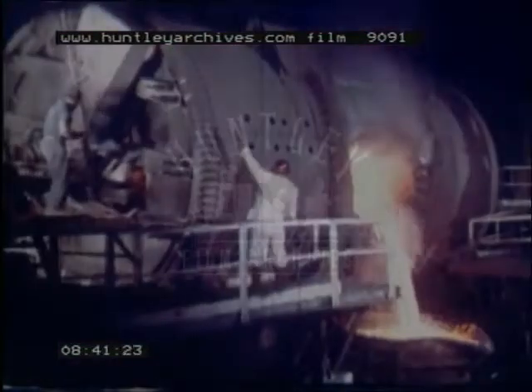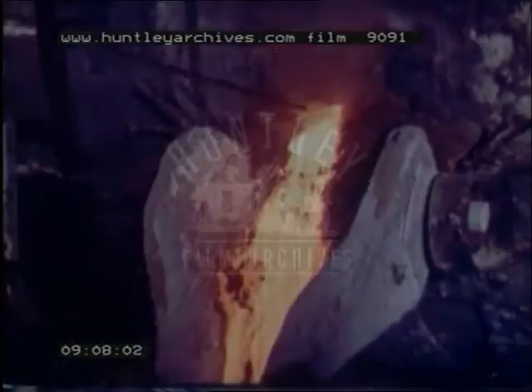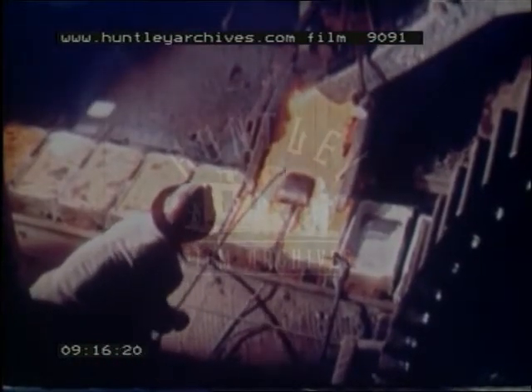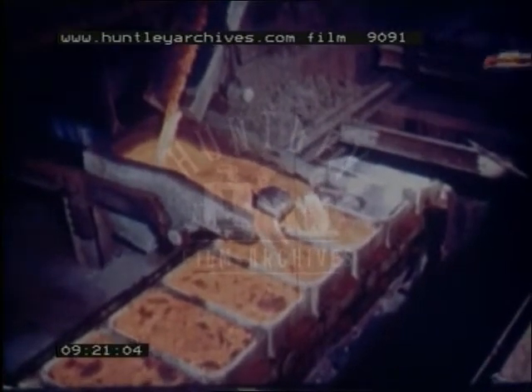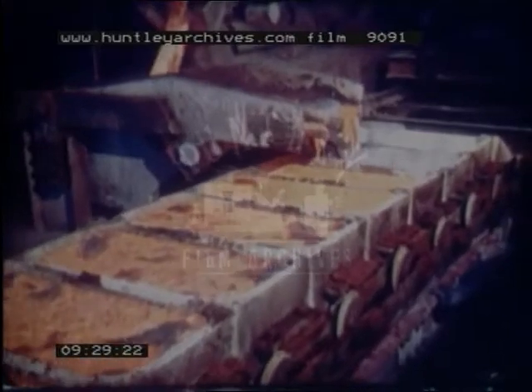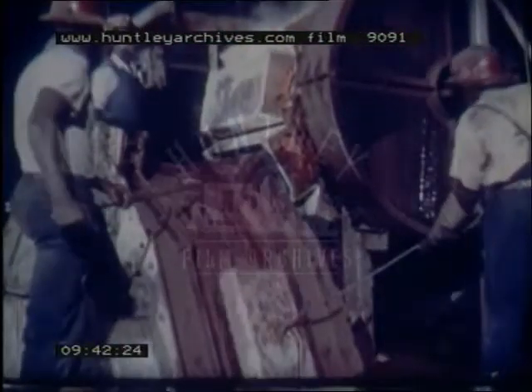The matte has now become crude copper called blister. The copper is taken to the casting furnace, thus freeing the converter for the next operation. The molten metal is cast into ingot molds. The ingots weigh from 300 to 400 pounds. They contain almost 99% pure copper. The Lubumbashi plant produces over 100,000 tons of blister copper each year.